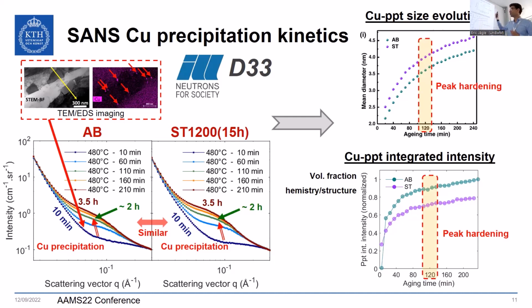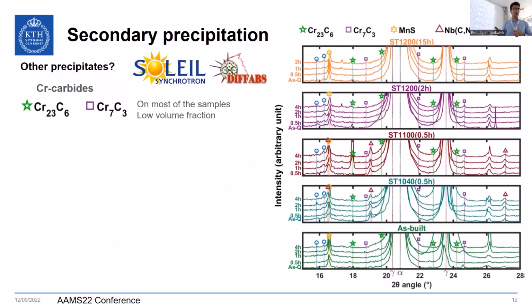And so that could explain why after that the mechanical properties could decrease, because if they're becoming bigger and lower in density, that's not the best. So what about other precipitates? We also have a few other precipitates, of course.